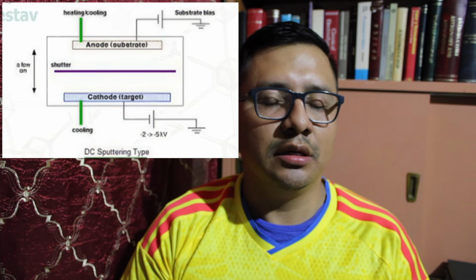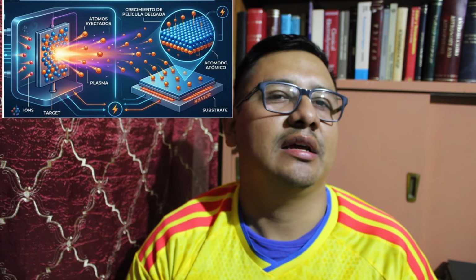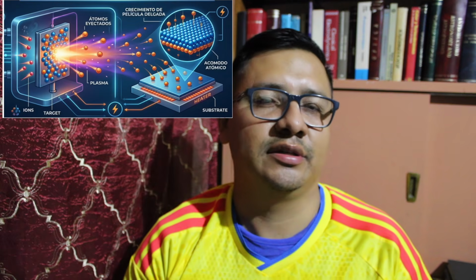In comparison with the DC sputtering system, the radio frequency system is alternating the polarity of the target where a magnetron is located, and this alternation of the polarity is reducing the contamination, or as we know it, the poisoning of the target, where the alternation of polarity is constantly cleaning the target surface.